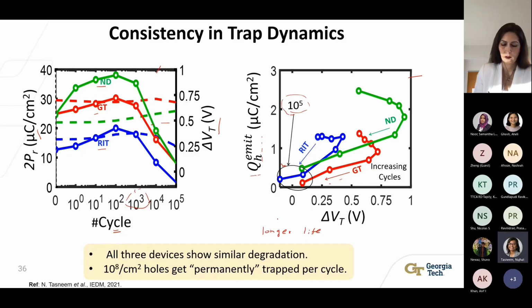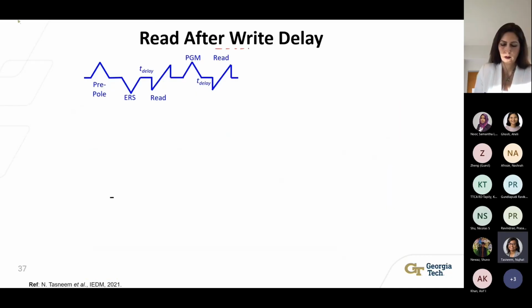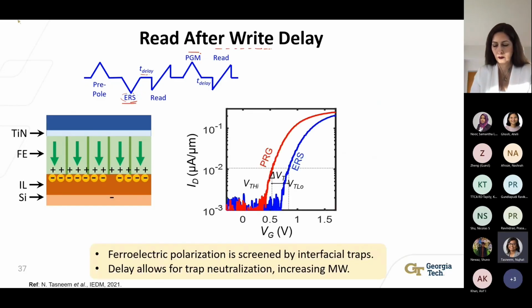In addition to this, we also tried to see how this read after write delay changes with fatigue cycling. Now, what is this read after write delay? This is the delay which is required to recover the memory window in an FFET right after a write pulse is applied on it. For example, immediately after an erase and program pulse, the ferroelectric layer in an FFET is polarized. However, the majority of this polarization is screened at the interface by trapped charges, and only a negligible portion of it goes into the semiconductor channel, which makes our memory window very low. For example, if the read after write delay was 1 millisecond, we would have got, say, around half a volt of memory window.